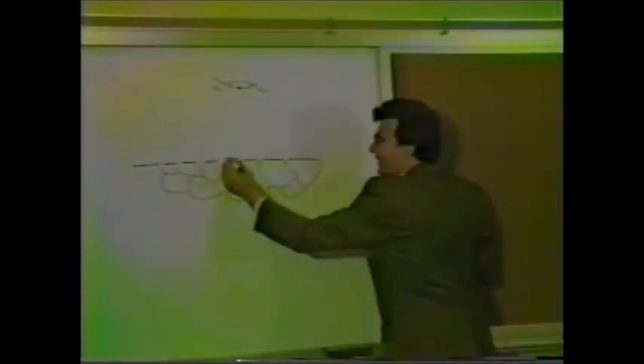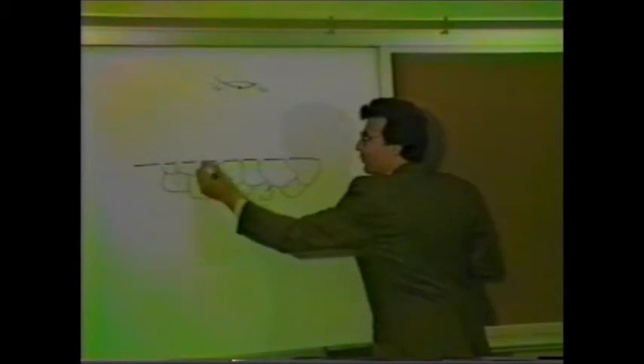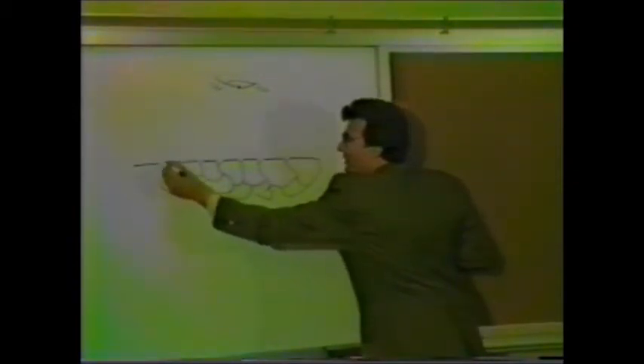And although it eats away the surface at one rate, it preferentially eats away the grain boundaries at a different rate than it does the rest of the surface. So what it does is it actually puts a little bit of relief into the surface of the steel. Now, you're asking, well, why is that important?